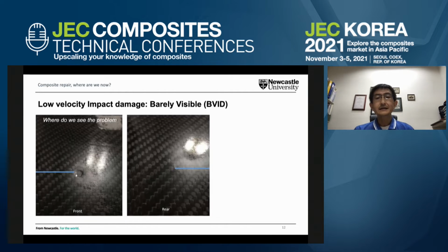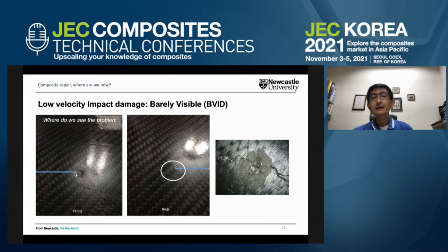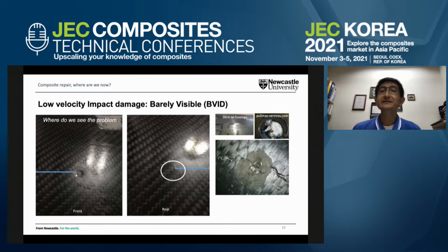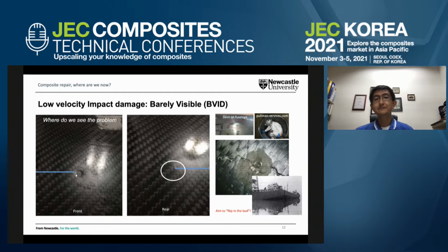But very often, it's what we don't see at the rear part. And that's where the crack line can occur. And these rear areas can be very inaccessible to us. And we know what will happen if we don't nip it in the bud, because there's a likelihood that the crack could propagate and lead to catastrophic failure.